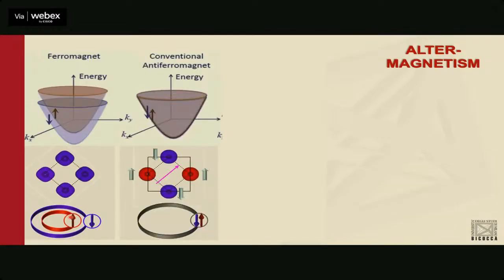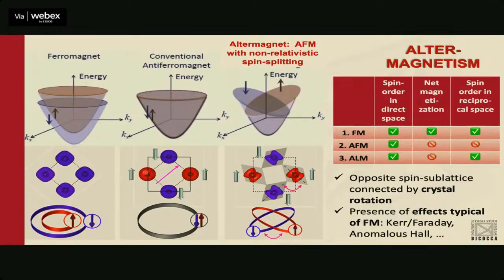An antiferromagnet, in real space, has up and down. But in reciprocal space, the electronic structure of an antiferromagnet doesn't show spin-split bands. The up and down bands are overlapped. So an altermagnet is something in between. Overall it has no net magnetization, so it's an antiferromagnet: if you measure the magnetization over temperature, you see nothing. But if you look at the band structure, there's a spin splitting. Along certain directions, you have bands that are spin up and bands that are spin down. And so you can generate spin current, or effects related to spin current, in an altermagnet.